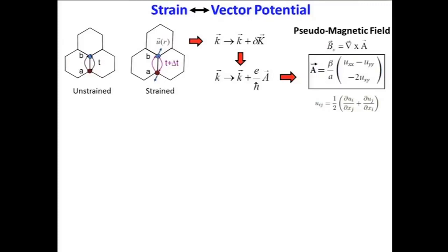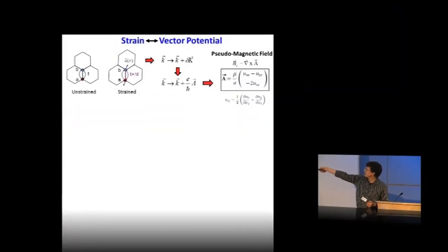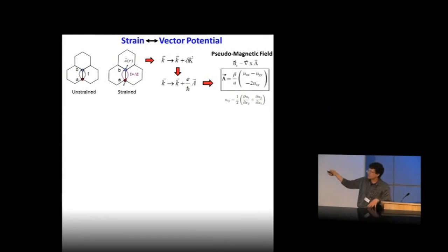Now, the reason that this occurs is because of a very intimate relationship that exists between strain in graphene and the electromagnetic vector potential. And one way of looking at this is to consider graphene, and now this is unstrained graphene. Now consider graphene that has undergone some amount of strain. You stretch it, and what that does is it causes the atoms to change their relative distance between each other. That then causes the quantum mechanical hopping amplitude to change for an electron to hop from one carbon atom to the other. And what that does is the electronic eigenstates shift in reciprocal space. Like this, that little delta k is meant to represent the shift of the graphene eigenstates in reciprocal space due to that strain.